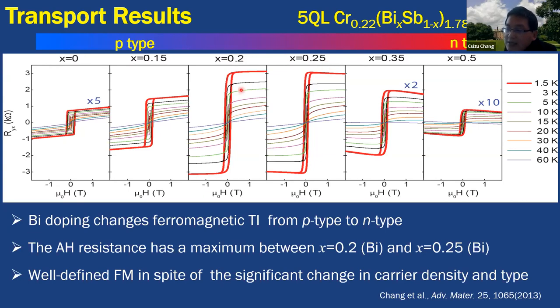And here we can see the anomalous Hall resistance actually shows a maximum when the x is between 0.2 and 0.25. That tells us when you reduce the carrier density in this kind of material, the anomalous Hall resistance becomes larger. So this is actually a good signature for the quantum anomalous Hall effect. And in all these samples, no matter the carrier type and the carrier density, it always shows ferromagnetism. As I just told you, this is just the basic requirement for the realization of the quantum anomalous Hall effect.